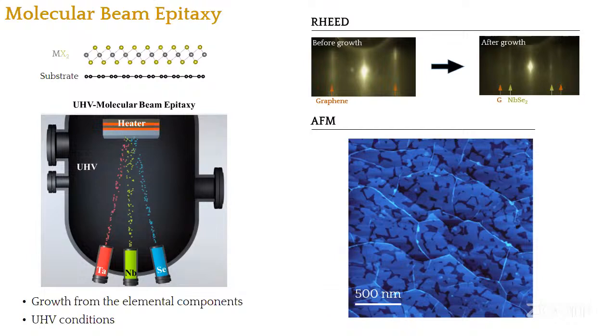If you grow MBE samples in general, you have bilayers already. And the way it grows in MBE, it grows in tiny islands that eventually coalesce. So it's not a single domain like in the exfoliated samples. Rotationally, it depends on the substrate. I agree. But in this particular case, the material grows at 0 and 30 degrees, but there is some sort of disorder. So if you want a twisted layer, there is some uncertainty. They're probably more bonded than these flakes. Probably, yes.